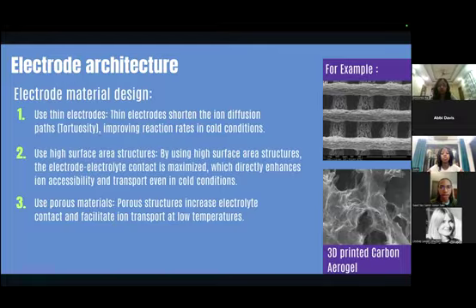Second, high surface area structures are crucial. By creating electrodes with intricate surface textures and patterns, the actual surface area becomes much larger than the geometric area. For example, what appears as a 1 square centimeter flat surface could actually have 100 square centimeters of real surface area due to its microscopic texture. And this dramatically increases the number of sites where electrochemical reactions can occur, maintaining high reaction rate even when cold